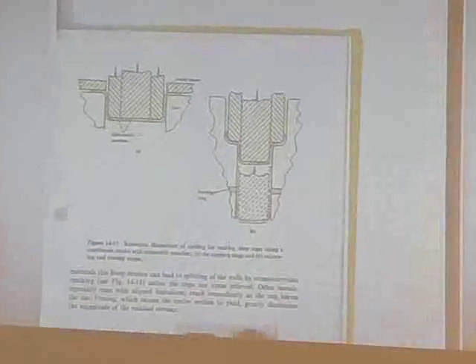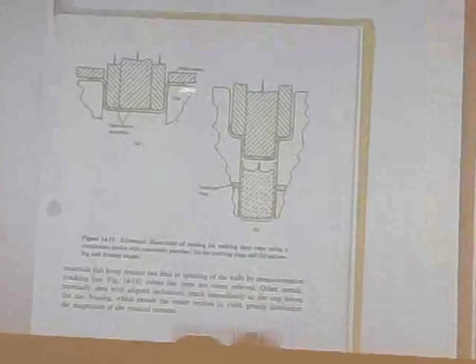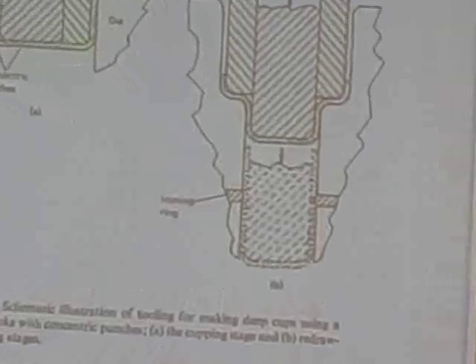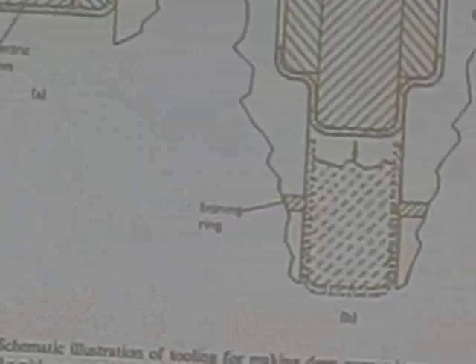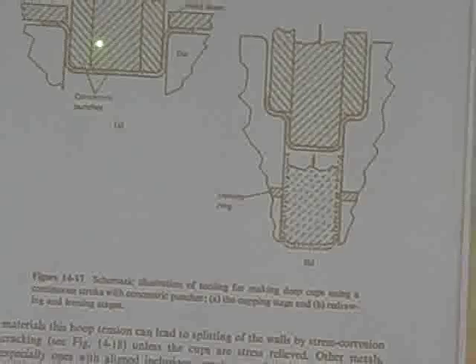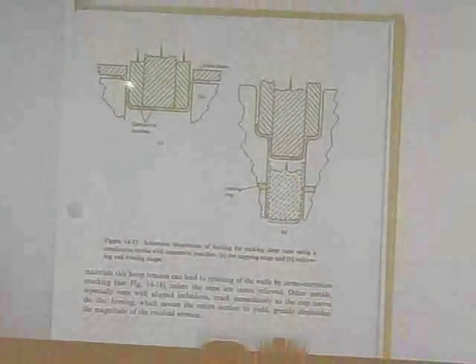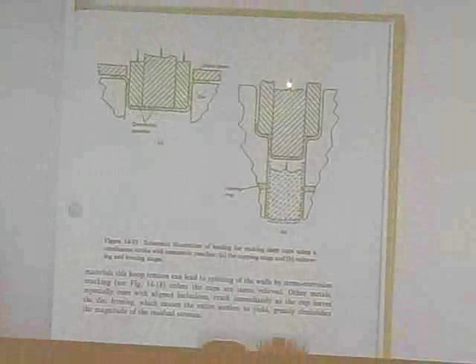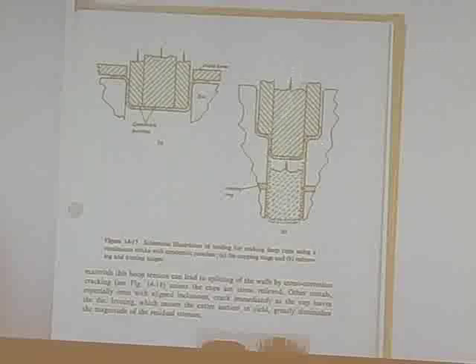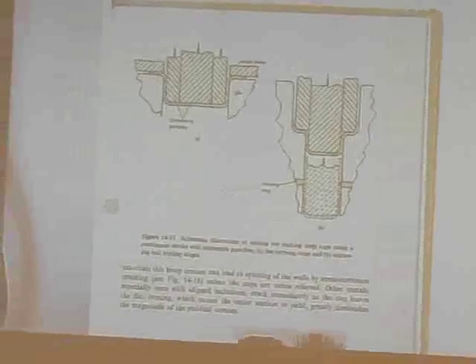This is basically a nice schematic that should be in your text. This comes out of Hosford, although it's from my second edition. But anyway, this is how you make a Coca-Cola can. You take a circular blank of aluminum, or in Japan a circular blank of steel, and you have some hold down clamps, which is part of the die coming down. And then you have two other dies in between, and the two center dies come down and draw a cup. And then the very center die, which is separate of the intermediate die, keeps on coming down and does a second draw. So you get two of your drawing operations in one stroke.